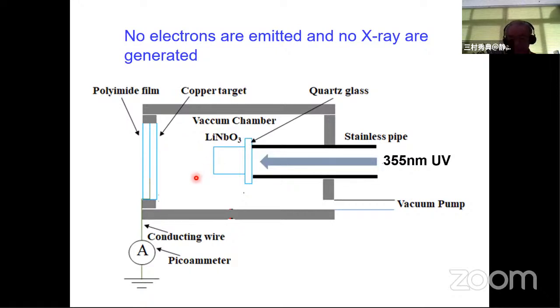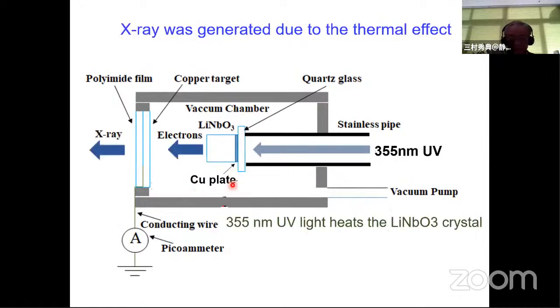Therefore, we inserted the copper plate between the lithium niobate crystal and the quartz glass. In this case, the 355 nanometer UV light heats the copper plate, and then the copper plate heats the lithium niobate crystal. In this case, X-rays were generated. Electrons are emitted from the surface of the lithium niobate, and the X-ray is generated, and it is due to the thermal effect.